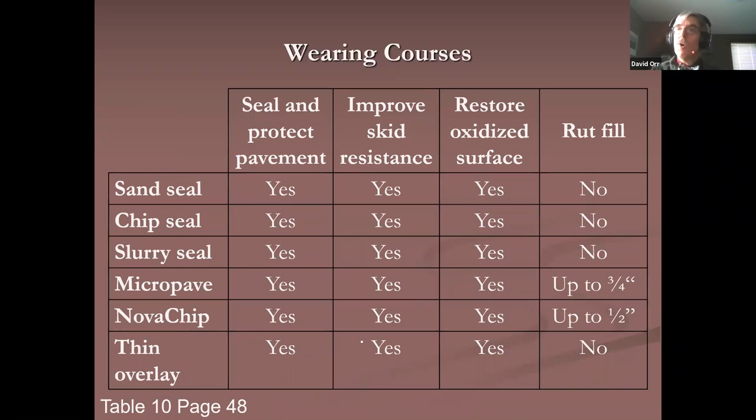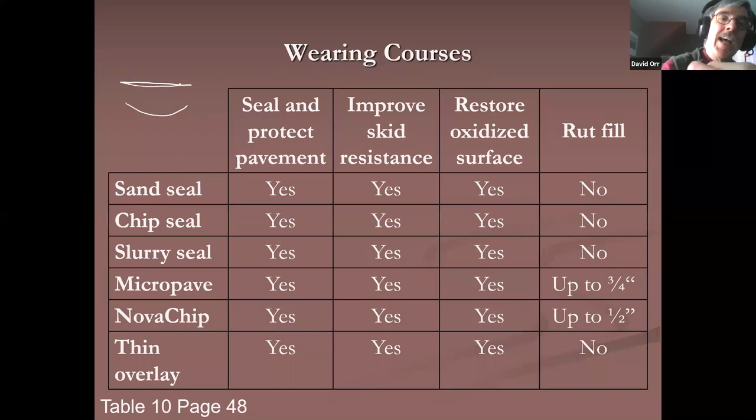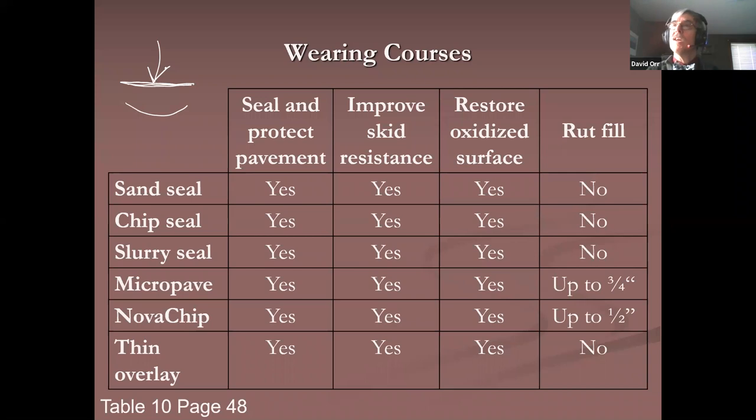A thin overlay won't, because when you try to fill in a rut with a thin overlay, it might be flat the day you did it, but what's gonna happen over time? Traffic is gonna come along, probably in the same spot where the rut was before, and it's going to rerut it. So thin overlays actually don't fill the ruts like most people think, okay?